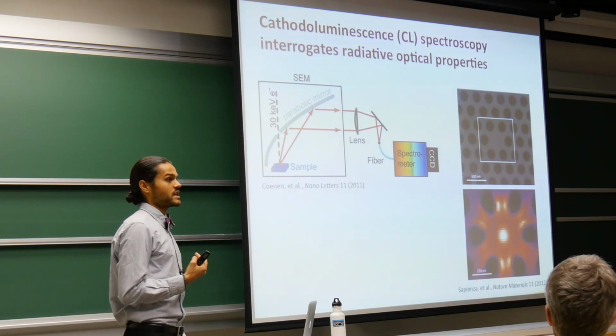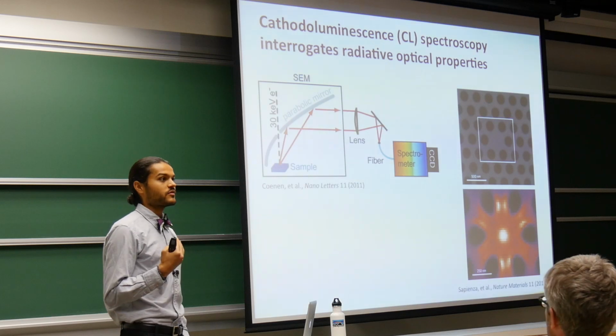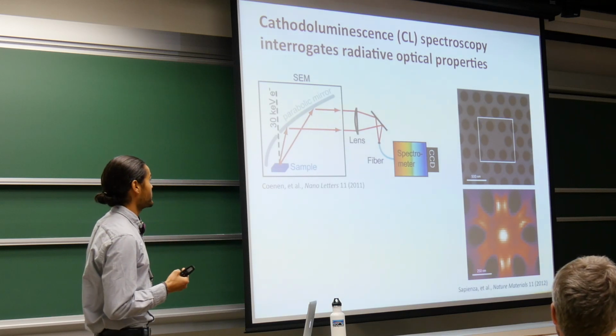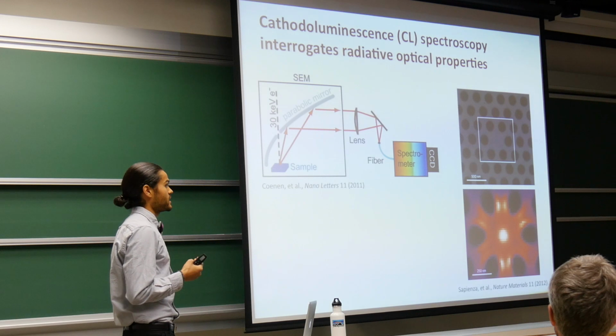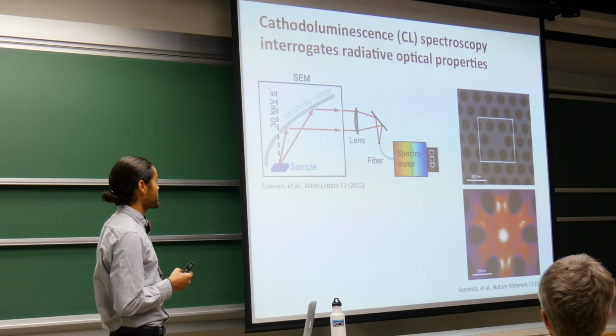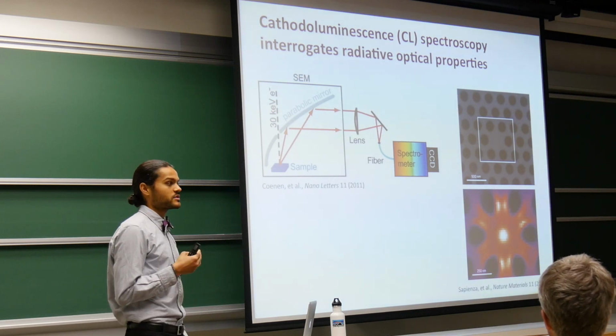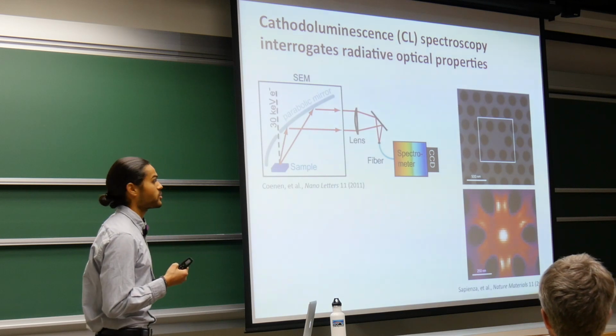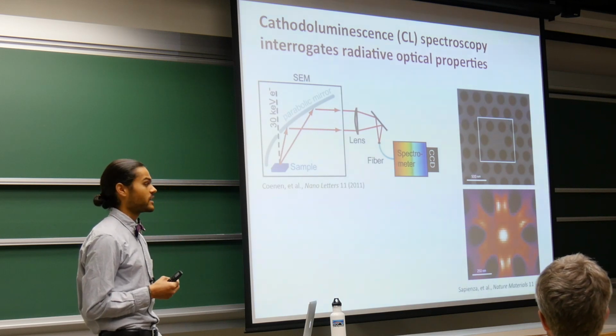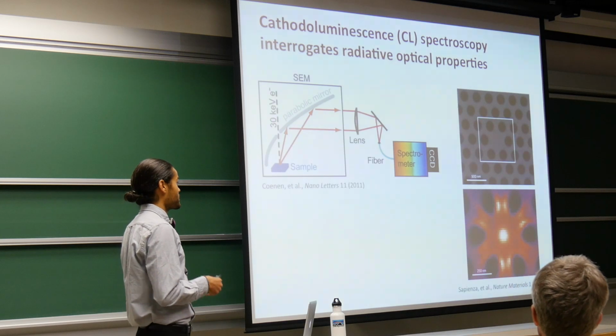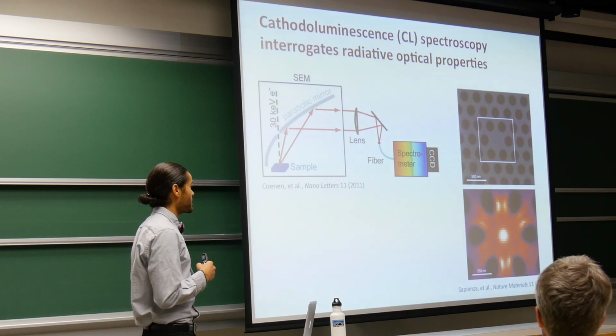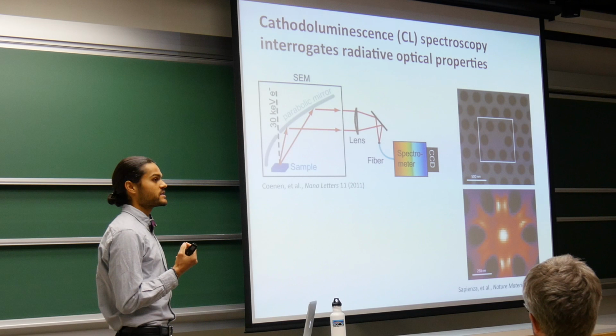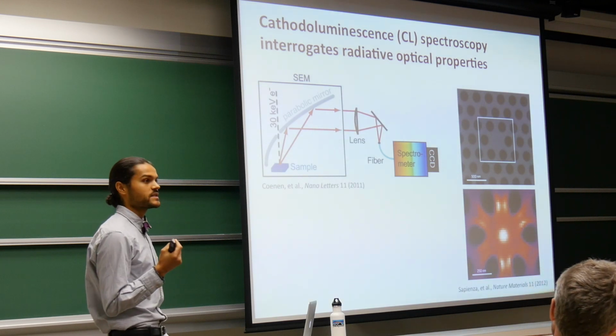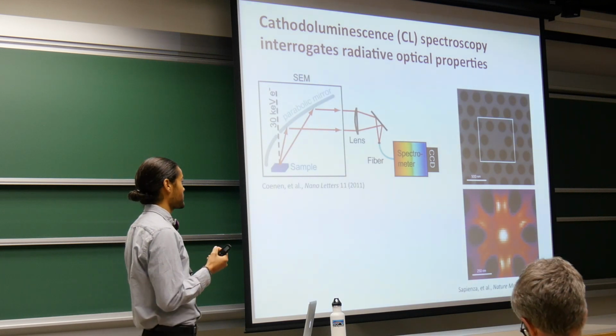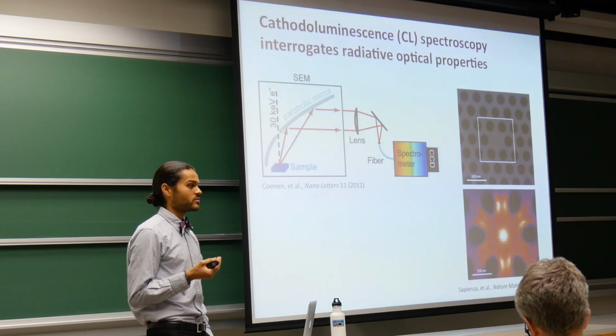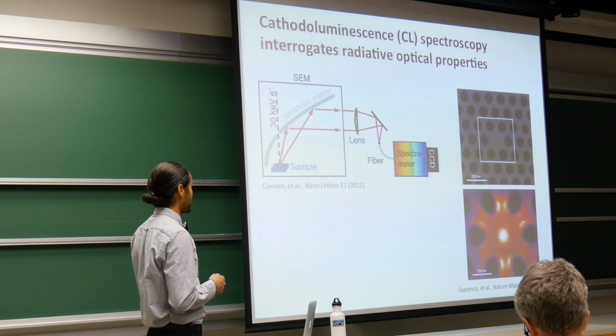Another really illustrative example of why cathodoluminescence is great for probing the radiative properties of a material: we look at this photonic crystal built into a silicon nitride membrane, where in this particular geometry, the cathodoluminescence signal is directly proportional to the radiative local density of optical states in this structure. So with this cathodoluminescence map in the lower image, we could use that, for example, to know where to place an emitting thing, like an upconverter, such that its emission properties were enhanced the most.